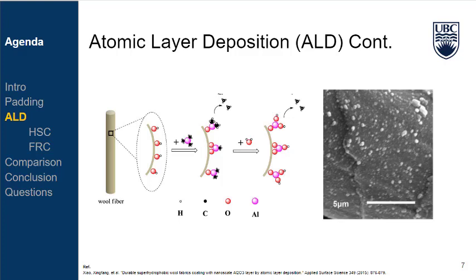In 2015, following the typical procedure mentioned before, ALD was used to transform the hydrophilic surface of wool fiber to superhydrophobic with a contact angle of 160 degrees. It is worth mentioning that to avoid issues brought by high temperature, which could trigger a considerable thermal degradation to wool fabrics as protein fibers, they used a relatively low temperature of 80 degrees Celsius.